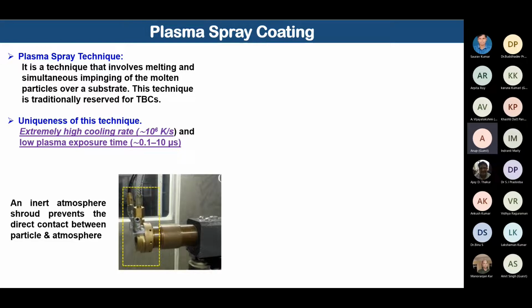And in this, even if some materials are very prone to oxidation, and we know that if we expose them to high temperature, there is a high chance that they will get oxidized. So for the safer side, we also pass an inert atmosphere, we pass inert gases, when we try to make the coating on the substrate. So basically this inert shroud cuts down the exposure of the molten powder particle to the environment.